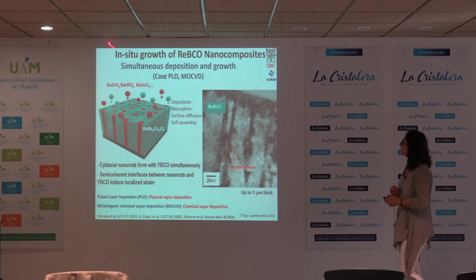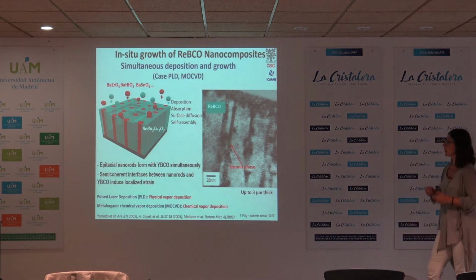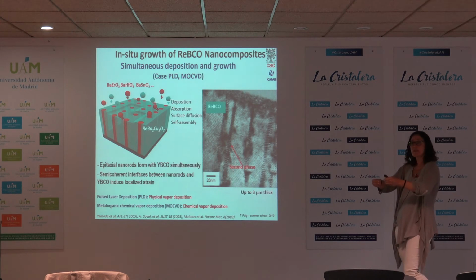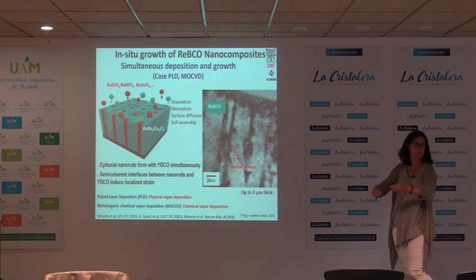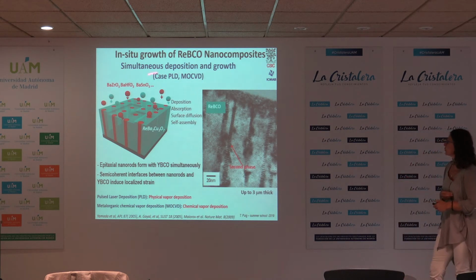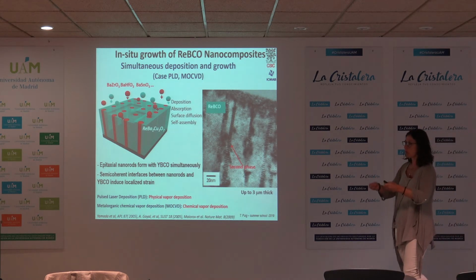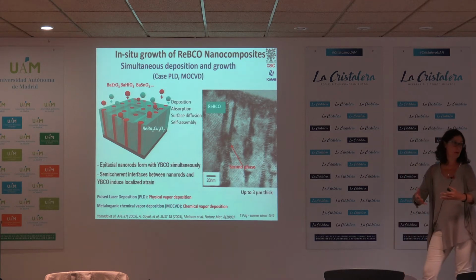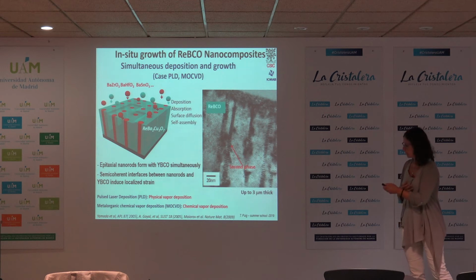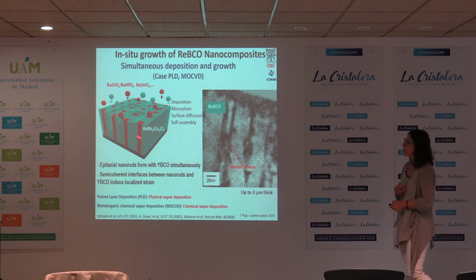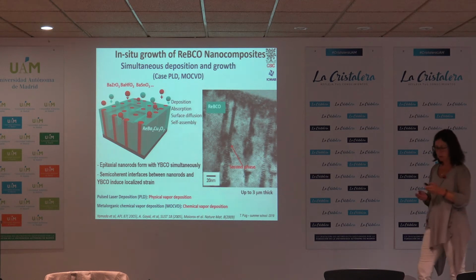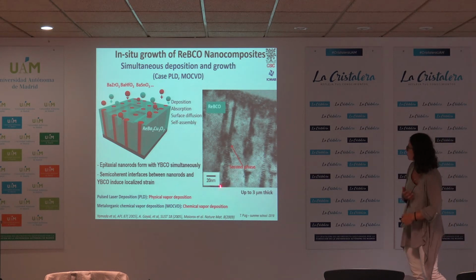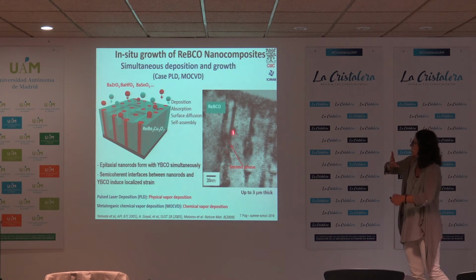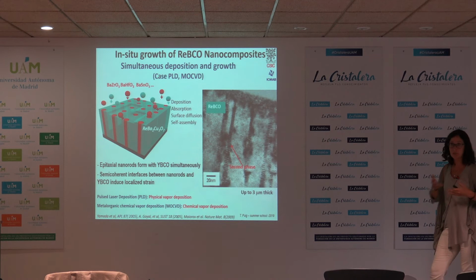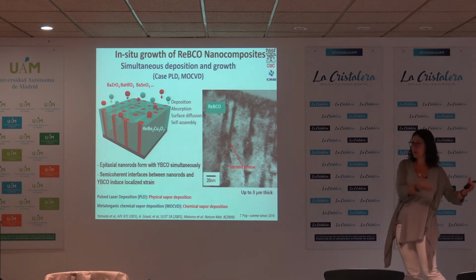Now, in the case that you want to produce these rods, that is done with processes where, when you deposit the YBCO material, you are also growing the YBCO material. This is the case of MOCVD or PLD. And when you want to grow the nanocomposite, you deposit both phases at the same time. One has to segregate from the other, and because they grow at the same time, you can benefit from the lattice mismatch, and you can end up with a strain which allows you to organize these nanoparticles in the form of rods. So there is an interaction between the growth of the YBCO and the growth of the nanoparticles.